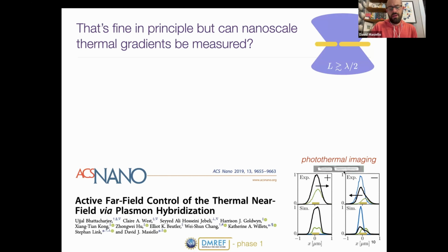And it turns out that the bonding mode localizes heat power preferentially on the long rod, and the anti-bonding mode preferentially localizes heat on the short rod. And so what they saw is they actually saw biasing in the photothermal image point spread function rightward or leftward that we were able with theory to tease out and correlate back to underlying thermal gradients that they were controlling with light, biasing rightward or leftward linearly in this dimer structure.